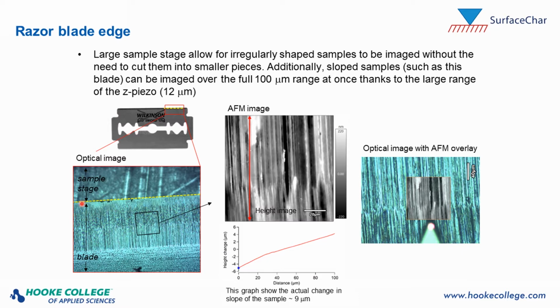And the reason that matters is, so if we can see here, the slope of that edge actually is about 9 microns. In a small sample instrument that has a Z range of only 5 microns, you would not be able to image that whole slope because you'd run out of Z range. But having this large sample instrument with the large Z range as part of it enables you to measure this entire range. And so not only do you get the full range, but now you can get a very high resolution image of the structure and morphology on this razor blade as shown here. This is our AFM topography image, and they can overlay that even onto the optical, so you can get a nice compare and contrast that way.